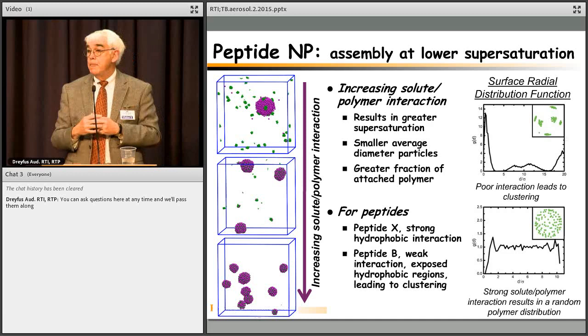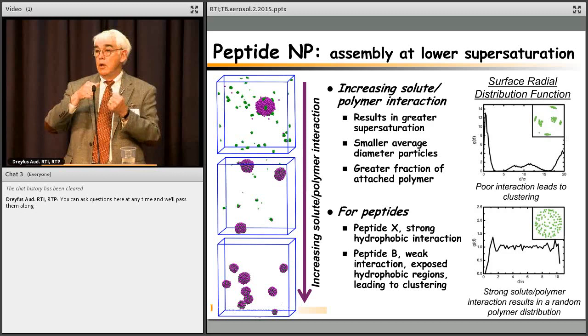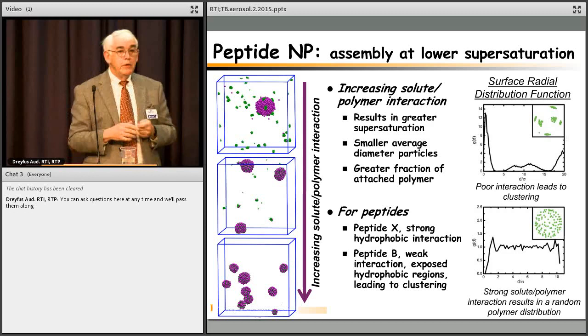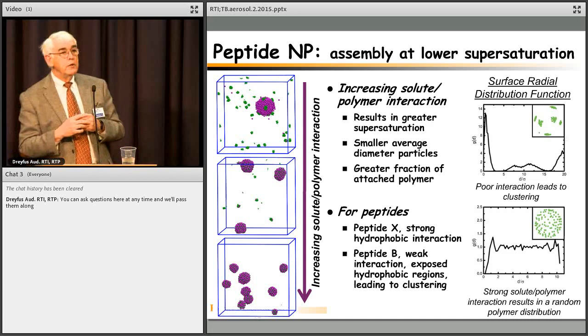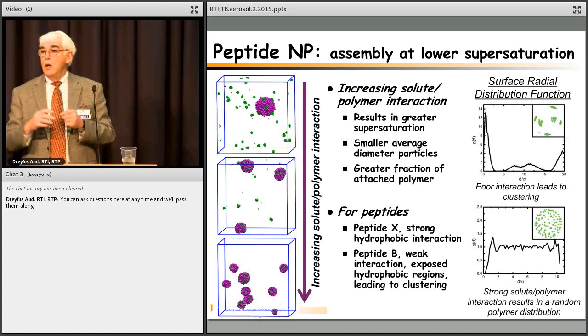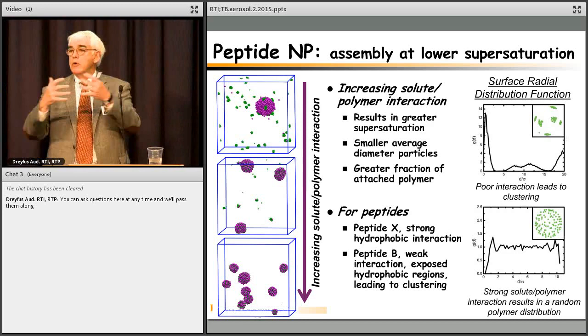What that does is those unprotected spaces then allow particle-particle aggregation. And you grow these things up until you finally have full surface coverage of these hydrophobic blocks on the surface. And this is a process which is called Pickering emulsions. If you're at all in this field, this is exactly the way that people make well-controlled emulsion sizes, by having a few stabilizing units making very small droplets and letting them re-aggregate up to dense packing on the surface. And that's basically what we've done here.